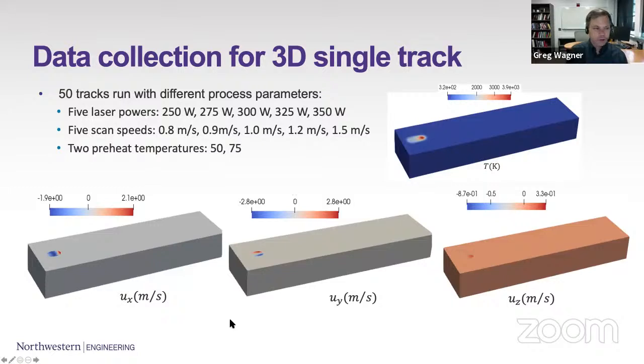In 3D, we're doing something similar, running our detailed simulations for different laser tracks. So this is a case where we're not tracking all of the moving interface. We're assuming that the interface stays fairly flat, but we are still solving now for the convection in the melt pool and the other physical phenomena at the melt pool.